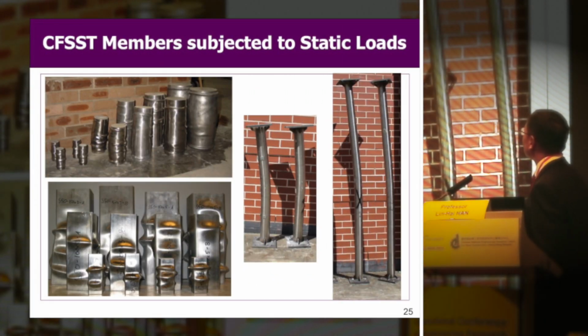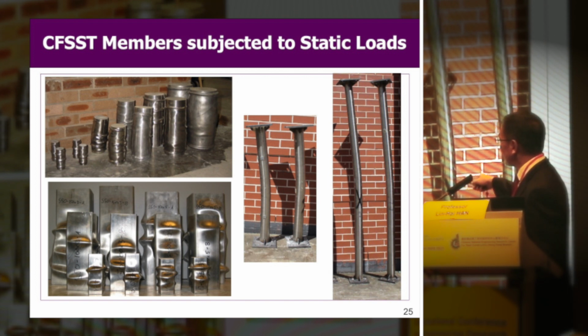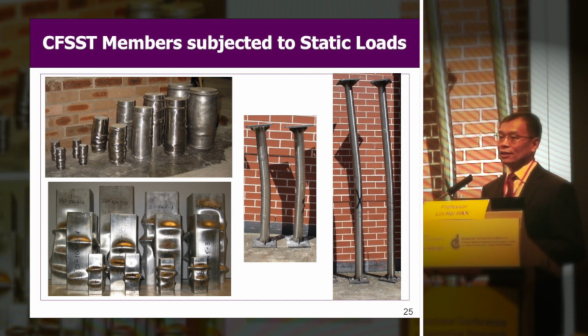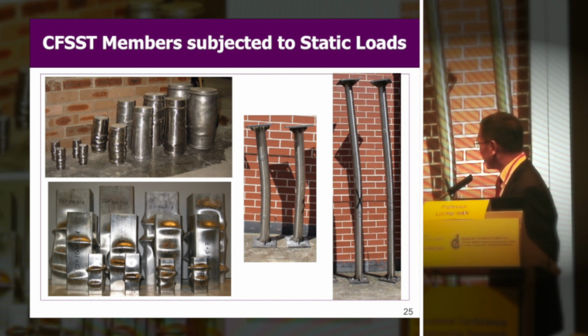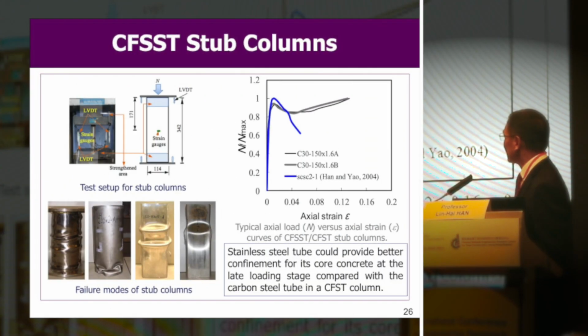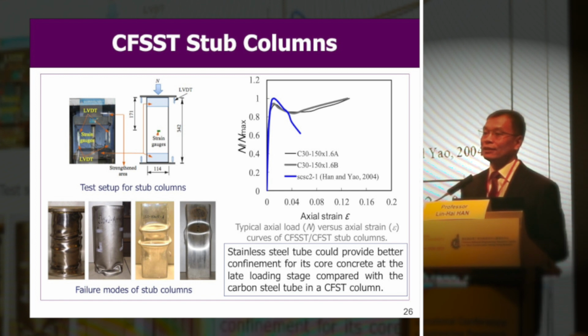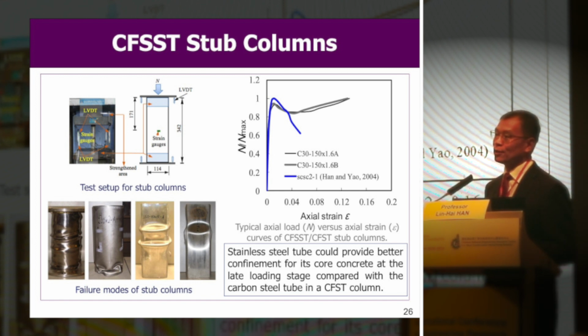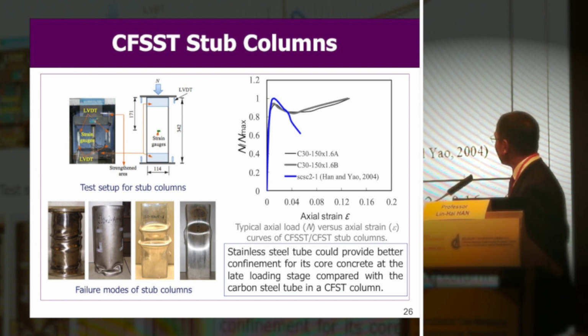So for the members under different loading conditions, you can see the smaller one, bigger one, to check the size effect. The very beautiful flattening mode, the longer column. And we have some comparisons of the compressive behavior of concrete filled stainless steel tube with the corresponding carbon steel tube filled with concrete. You can see the full response of the loading and the axial strain.